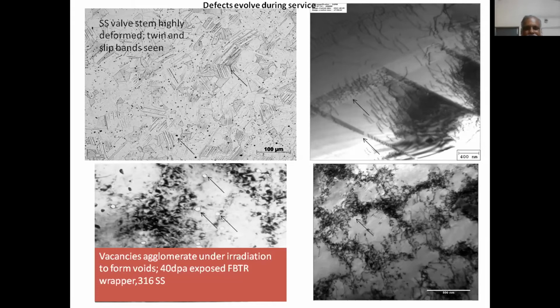The vacancies agglomerate over a period of time, and that is called evolution in the form of voids. These nano voids can be seen only in TEM. You see these white dots are basically voids, the white round ones. How do you say they are voids? A person who has worked with a transmission electron microscope knows that the electrons travel through the sample. If they get scattered, the image will become dark. If they pass through the sample, it will become white.